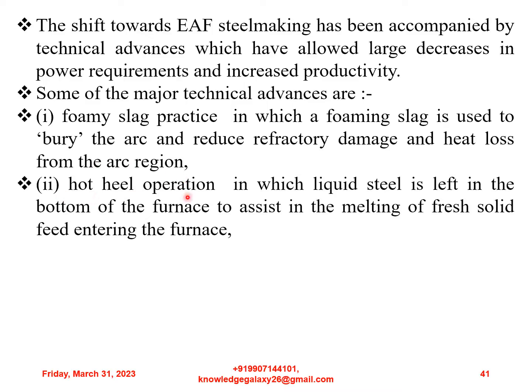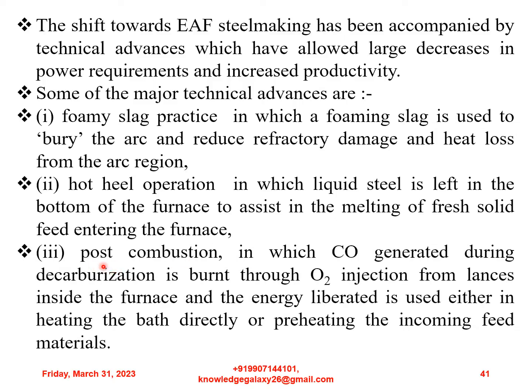Next is hot heel operation, in which liquid steel is left in the bottom of the furnace to assist in the melting of fresh solid feed entering the furnace. Next is post combustion, in which CO generated during decarburization is burned through oxygen injection from lances inside the furnace, and the energy liberated is used either in heating the bath directly or preheating the incoming feed materials.